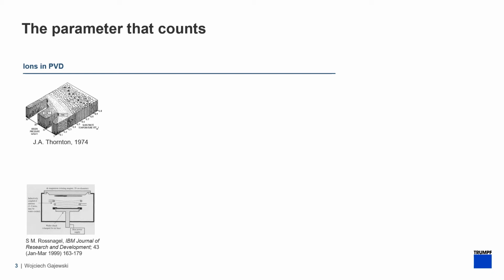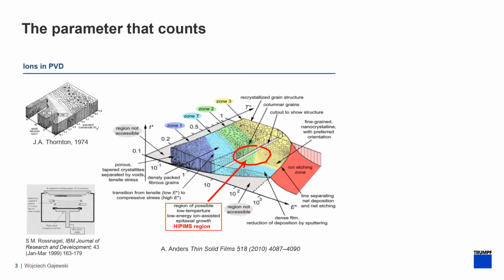Development of plasma processing for the semiconductor industry is interesting, but not the main topic for today. The key message from here is that not only pressure, not only temperature of the substrate, we should be able also to control the ion energy, because when we can do that, we can go from very fine structure of the coating which we deposit to the ion implantation and etching.